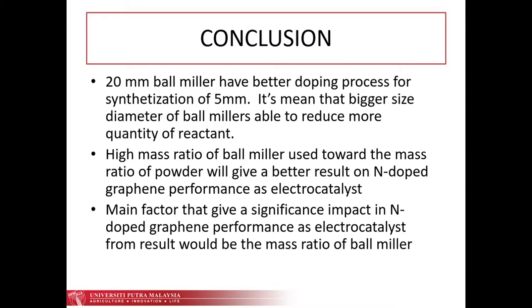As a conclusion, the 20 millimeter ball miller has a better doping process for synthesis of nitrogen doped graphene compared to 5 millimeter. So a bigger diameter of ball miller is able to reduce more quantity of reactant. The second conclusion is that a high mass ratio of ball miller used toward the mass of powder will give a better result on N-doped graphene performance as electrocatalyst. As we know from the analysis, sample 1 has the highest mass ratio of ball miller, so it gives the best result of N-doped graphene performance.